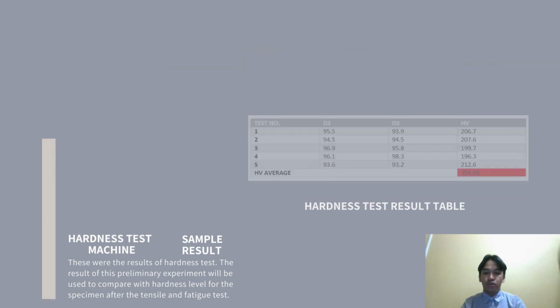The other experiment that I have carried out during this FYP1 is the hardness test. The method of the hardness test is the Vickers hardness test. As we can see in the picture, this is the hardness test machine and the sample result of the experiment. I have done the experiment 5 times and got the average value for the Vickers hardness. These were the results of the hardness test. The result of this preliminary experiment will also be used to compare with the hardness level for the specimen after the tensile and fatigue test that will be carried out during FYP2.